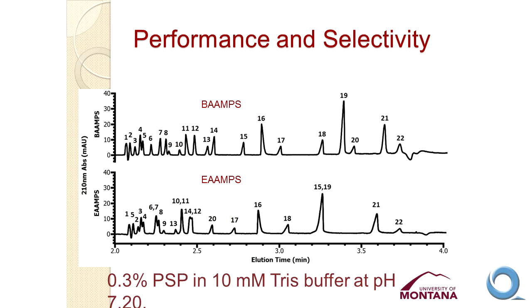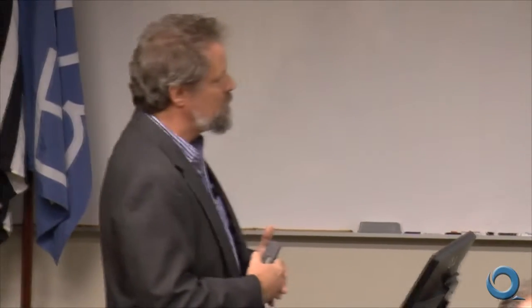We, again, don't fully understand what's causing that. The other thing that we can see is these 22 compounds are numbered in the order of elution on the butyl acrylate nanoparticle. And if we compare that order on the ethyl acrylate, we can see some significant differences in the position and the relative migration times of these peaks. So that tells us that the ethyl acrylate core gives us quite different selectivity from the butyl acrylate core.